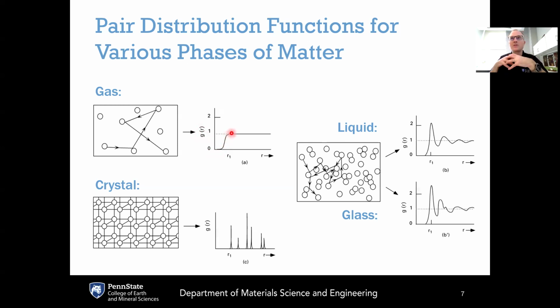So once you get past the regime of atoms overlapping each other, the structure after that is totally disordered. And so the G of R just goes directly to 1. And this would be for a monatomic gas. If you have a diatomic gas, like oxygen gas or nitrogen gas, then the first nearest neighbor position is very well defined by the bond, like the oxygen-oxygen bond or the nitrogen-nitrogen bond, but then you'd have complete disorder after that.